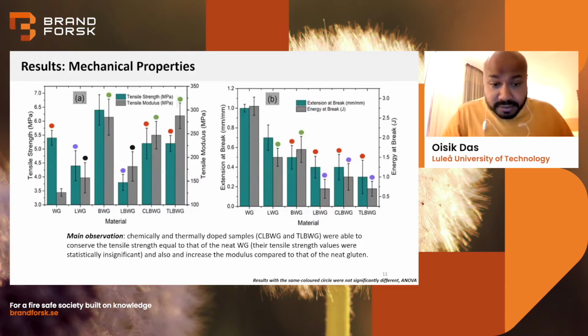After we made the composites, we tested the mechanical properties. What we have seen is that with the chemical doping method and thermal doping method, the tensile strength of those composites was the same as the control sample, which is the neat bioplastic, and the tensile modulus was much higher than the control sample, which is good news, because that is what we are trying to do. We are trying to conserve the mechanical strength and improve the tensile modulus by adding fire retardant and biochar. Although the ductility has reduced, nevertheless the tensile strength has been conserved.